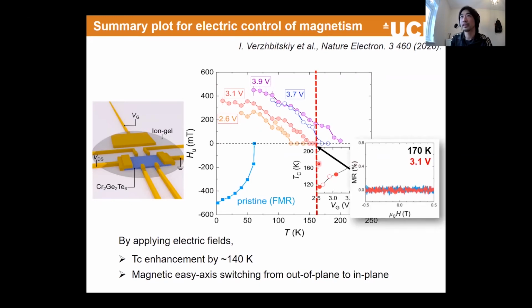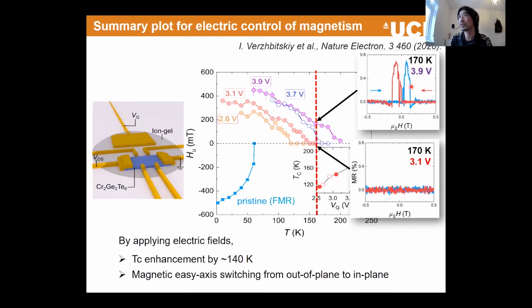All right, so this is just a demonstration, just sitting at 170 Kelvin, applying 3.1 volts, nothing happens, but as soon as you apply 3.9 volts, just up by 0.8 volts, you can see that we can create the magnetism. So we just switch on and off this magnetic behavior by just applying a different voltage. So that's nice to see.